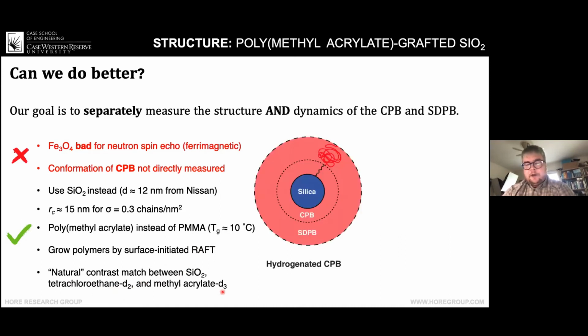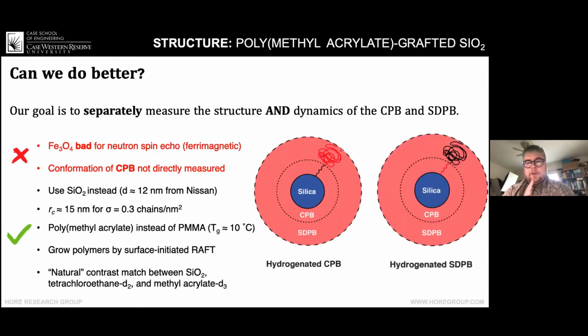But the objective here is that for one set of samples, we can hydrogenate the concentrated region and deuterate the semi-dilute region, and then switch that deuteration scheme for the second set of samples. So in one, we will highlight the scattering from the concentrated region and hide the scattering out here. And in the other sample, we'll reverse what we're seeing with the neutrons.